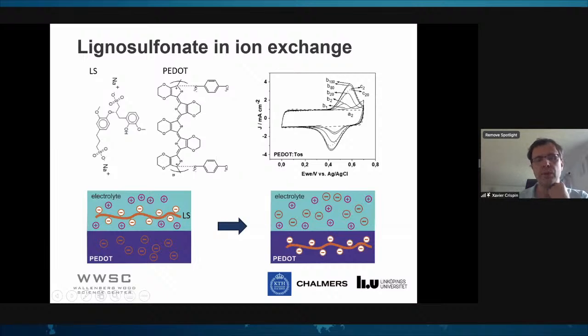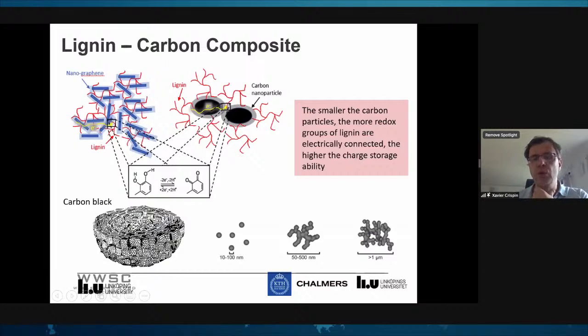What we can look at is also what to do with the carbon. You can buy very cheap carbon, like carbon blacks. But if you just use carbon black and lignin and mix them together, you're not going to have any great material, because there are a lot of parts of lignin that are not close enough to the conductor to undergo an electron transfer. That is going to be basically dead volume for the storage of electricity. It's only at the very close vicinity where the electron can tunnel into the lignin, which is an insulator, that you can have charge storage.